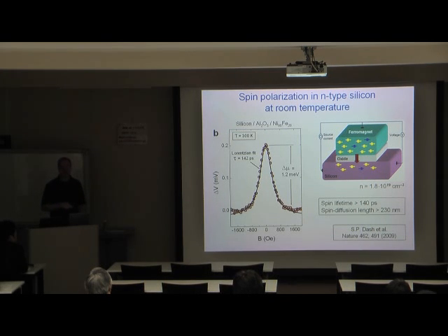the lifetime, which comes out to be about 142 picosecond, and in principle the spin lifetime is about 142 picosecond, but I have written here a larger than sign. I will explain in the second part of my talk why there is not an equal sign but a larger than sign. For the moment, this is the spin lifetime in silicon.